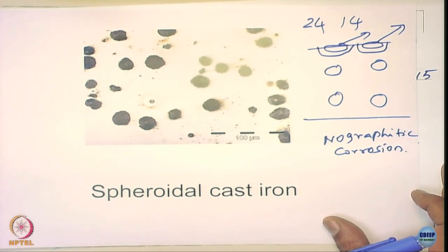If you compare the cast iron versus the steel, generally the cast irons corrode at a lower rate. I am talking about uniform corrosion, because the cast irons may have some silicon, all the stuff, so they are generally more resistant to uniform corrosion. But if you have gray cast iron, the problem comes out of the localized attack that happens between the graphite and the iron matrix, leading to leaking of the pipelines. People in those days were storing even sulfuric acid using cast iron tanks, and sulfuric acid would leak from inside to outside. The whole structure looks very intact, but it oozes out because the corrosion occurs between the graphite flake and the matrix, and so starts oozing out from the surfaces. So, the only way to avoid this is not to use gray cast iron; people use what is called a malleable cast iron or the nodular cast irons, okay.